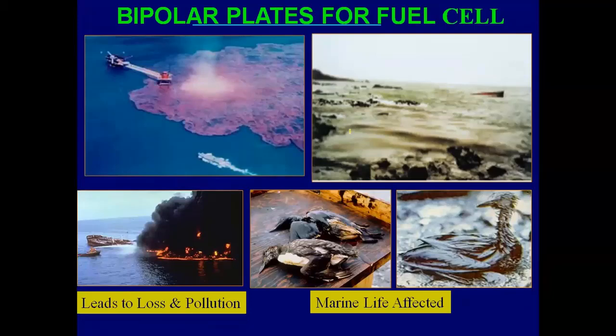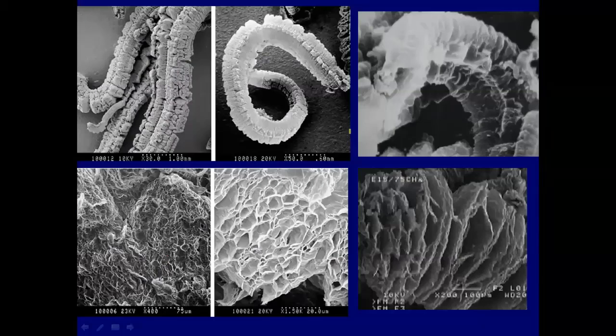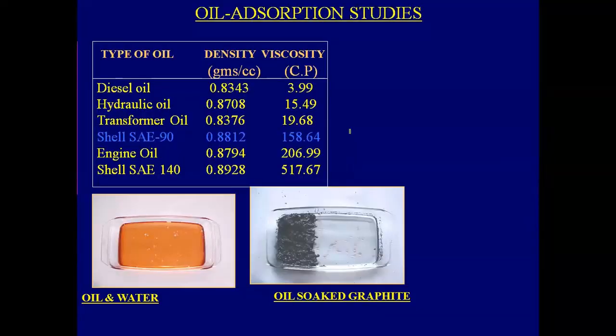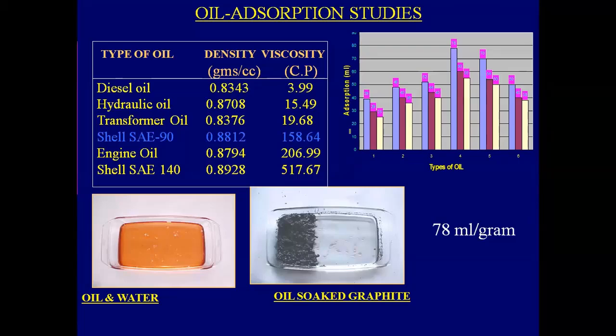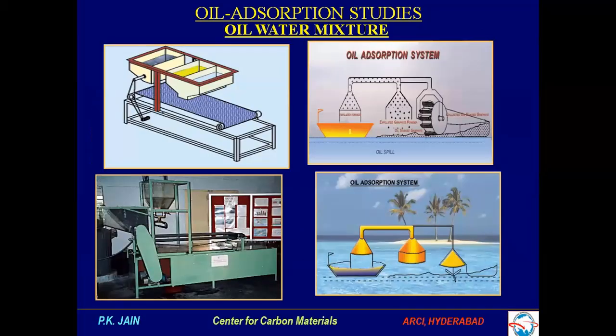Another important application of this graphite is in oil absorption. Oil spills are very common in many places, knowingly or unknowingly, and they lead to a lot of marine birds and other animals, mammals, getting affected, which is not good. This porous carbon has high porosity. These pores act as capillaries, and whatever oil is on the surface will be absorbed, and you can recover around 78 to 80 ml of oil per gram. You can recover the oil back, and I was holding a patent for this.